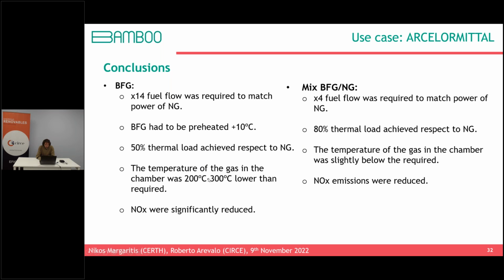The temperature of the gas in the chamber with BFG was 200 to 300 degrees lower. This is to be expected also. Instead, when we use a mix, the temperature of the gas in the chamber is just only very slightly below the required. NOx emissions are significantly reduced in both cases. Of course, with BFG, they are more reduced because the temperatures are lower. But the main point is that when we use a mix of BFG and natural gas, they are also reduced.